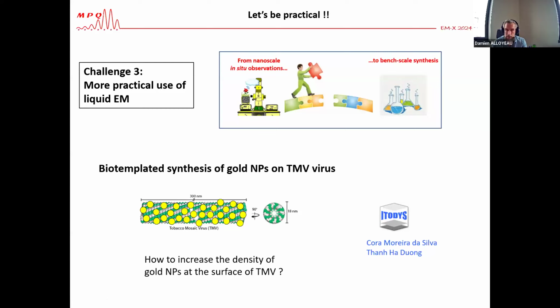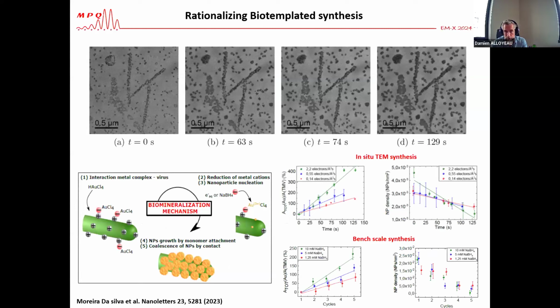So the challenge they wanted to meet was very simple: how can we increase the density of gold nanoparticles at the surface of TMV? So we have done the same experiment as before, except that we have the TMV viruses inside the liquid cells. And from the mechanistic point of view, we have been able to confirm that the nanoparticles don't form in solution and then graft to the viruses. They really form on the viruses because there is an electrostatic interaction between the precursor and the surface of the virus. You have the reduction of your metal precursor, the growth, and the very rapid coalescence of the nanoparticles.